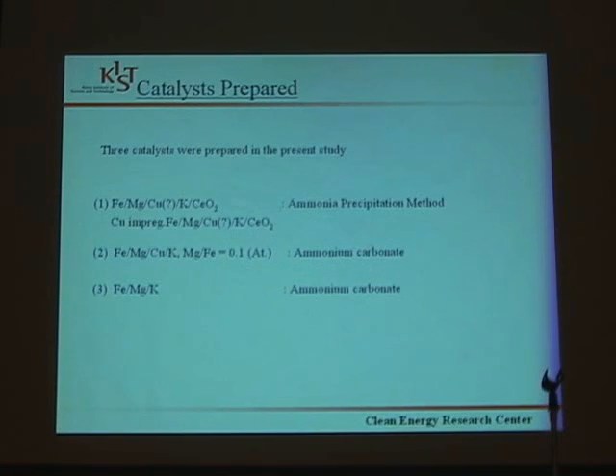So in the present study, we actually prepared 3 types of catalyst. First is iron, magnesium, copper, potassium and cerium. In this catalyst we used magnesium, copper and iron nitrates for the precipitation first, and then impregnated with potassium. Ceria was also used as a support, but it was introduced during precipitation only. Secondly, this same catalyst we again impregnated with copper nitrate. The second catalyst we prepared is magnesium promoted precipitated iron catalyst, later impregnated with copper and potassium. And third is iron precipitated catalyst, later impregnated with potassium and magnesium.